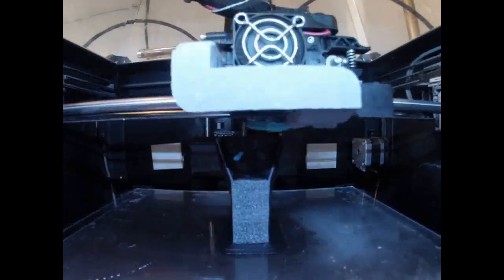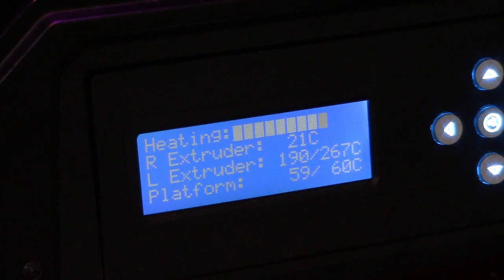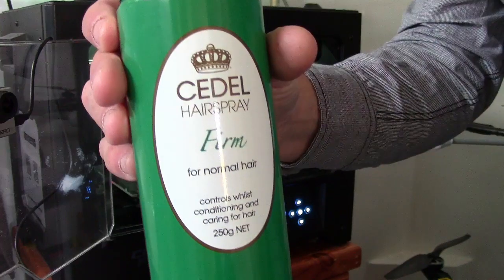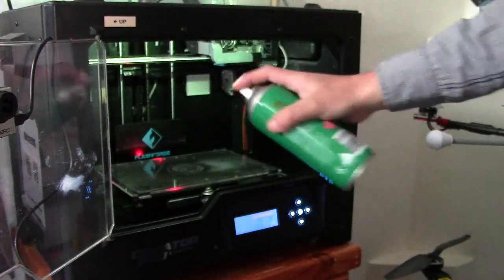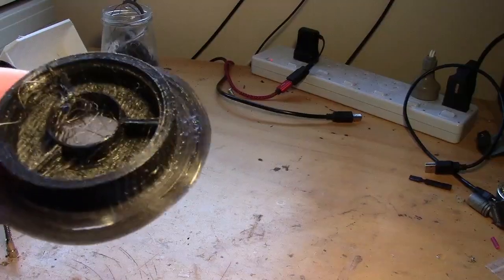Because the motors can get hot, PET can get soft and fail, and so nylon is a good choice. As you may know, nylon requires a higher print temperature than other common materials, so you'll need to fit an all-metal hot end to your printer. Poor bed adhesion is a real challenge of working with nylon. I found using a thicker first layer extrusion width and a squirt of hairspray on my glass print bed does